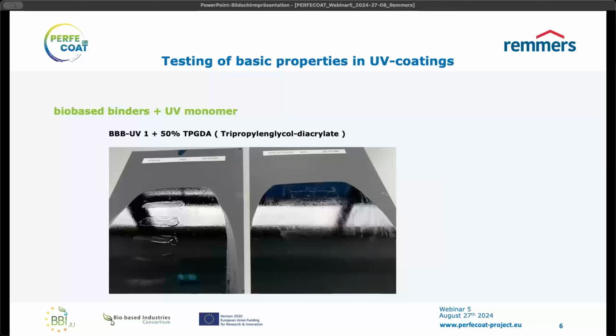And here you see what happened when the binder number 1 was mixed with 50% of TPGDA, which is a commonly used tripropylene glycol diacrylate. And indeed, it got much better, like you can see here in the picture. The film is not wet anymore, like it was with the pure binder. But there was still some smeary surface. So the very top 1 or 2 micron of the film are still not curing sufficiently. But this was showing us for sure that with checking such mixtures with UV monomers, we're in the right direction.